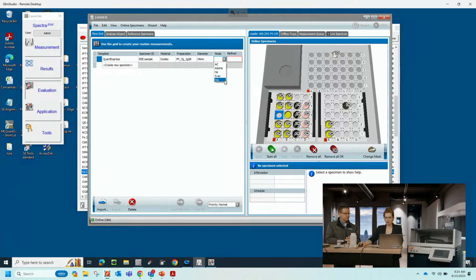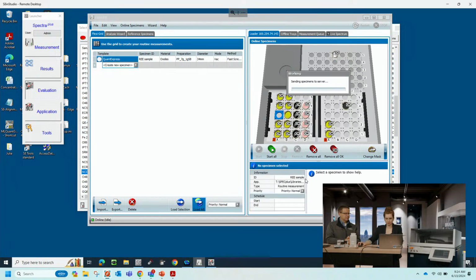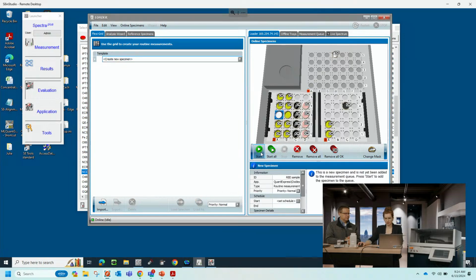And then I can measure this in vacuum, and I'm going to use the really, really fast measurement because I think it's really impressive how fast this goes. So we're going to put this over here, and then we're going to start it. I mean, this is really self-explanatory. And so what we're going to see is, hopefully, this is a little farther away, but you will see that the grabber in the back is going to go to the front to pick up the sample that I just defined. There you can see it.